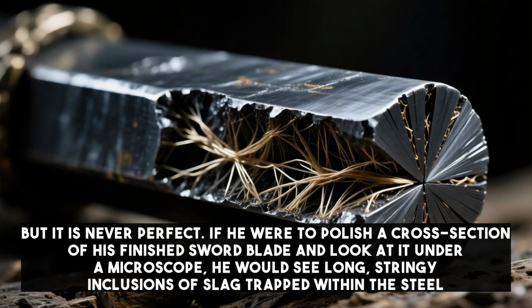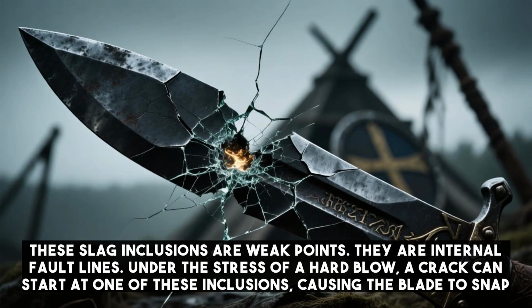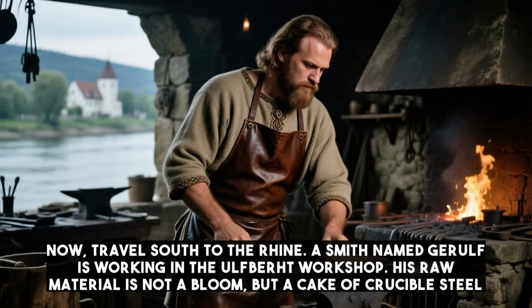If he were to polish a cross-section of his finished sword blade and look at it under a microscope, he would see long, stringy inclusions of slag trapped within the steel. These slag inclusions are weak points. They are internal fault lines. Under the stress of a hard blow, a crack can start at one of these inclusions, causing the blade to snap.